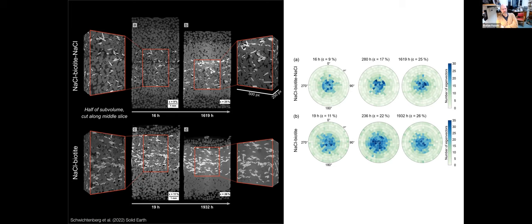Also, and that was very interesting, these are now looking at the biotites. We isolated the biotites and we followed them through time. Essentially, what we have here is a lot of halite grains, and they point load the biotites. So we did expect the biotites to rearrange themselves, as you would expect for a proper foliation, essentially all becoming parallel. Now, these diagrams here, you may recognize, are stereo plots. They show the eigenvector perpendicular to the basal plane of biotite. So essentially that rotates. And in fact,